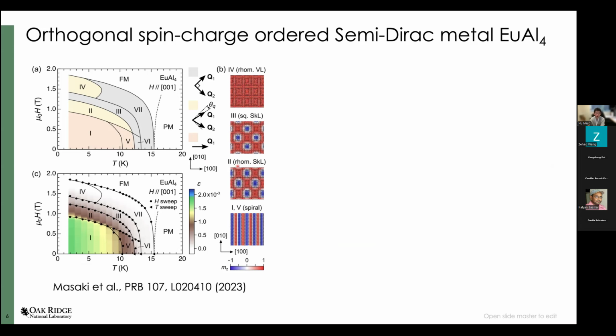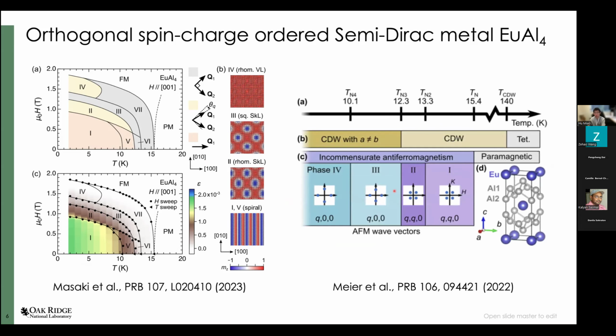If we focus on zero field, here is the phase diagram, and if you zoom out the temperature axis, you see the CDW emerges around 140 Kelvin, about one order of magnitude higher than the spin density wave or skyrmion phase. So basically, this material features spin and charge density waves, topological spin texture, and a topological electronic band structure. That's the reason why we are interested in this material.